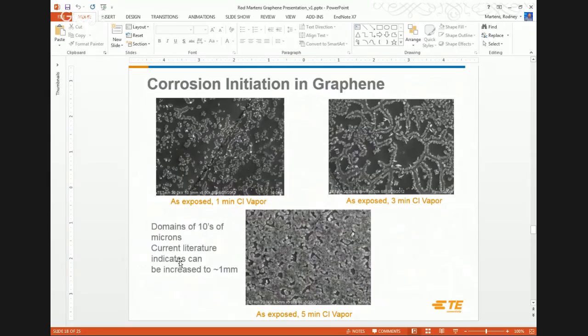So we'll move away from kind of the mechanical interrogation of the film to the corrosion. So to be honest, my concern with a lot of hype about graphene, carbon nanotubes, etc., is we project these wonderful properties from the nanoscale out to the macro scale. And typically you can't achieve that, and the main reason for that is defectivity.